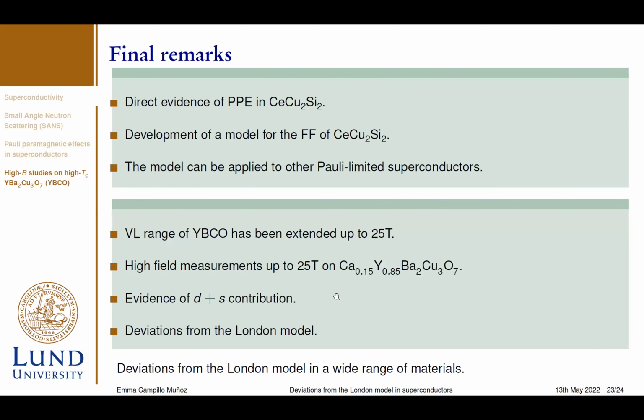So finishing this talk, we found direct evidence of paramagnetic effects on cerium copper 2 silicon 2, and we successfully developed a model to describe the behavior of Pauli-limited superconductors that not only works for cerium copper 2 silicon 2, but also works for cerium cobalt indium 5. And we aim to use these kinds of models in all the not well-behaved superconductors. So we may use this model to maybe describe possible paramagnetic effects on the YBCO sample.